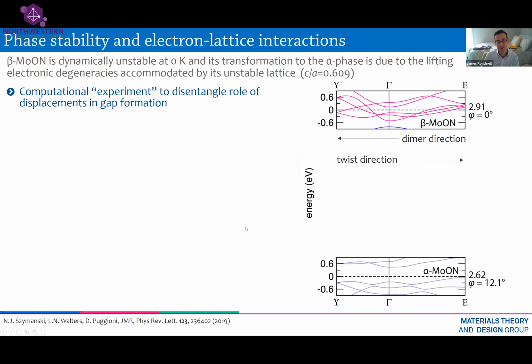And if you wanted to understand in more detail how this occurs, again, connecting changes in local structure, as I introduced in the beginning, to changes in electronic structure, here are the spaghetti plots, or the band dispersions for that sequence of phase transitions. And we know how the two structures are connected, the beta phase and the alpha phase, via a dimerization and a twist. Instead of looking at the density of states, we can look at how these bands disperse in momentum space. And again, the Fermi level here is at 0. And what I'm looking at is the distribution of these states in the reciprocal lattice.